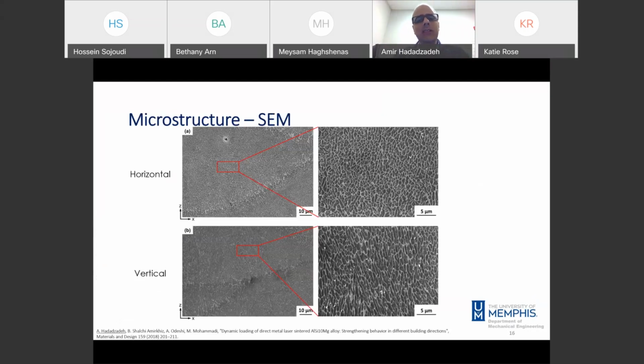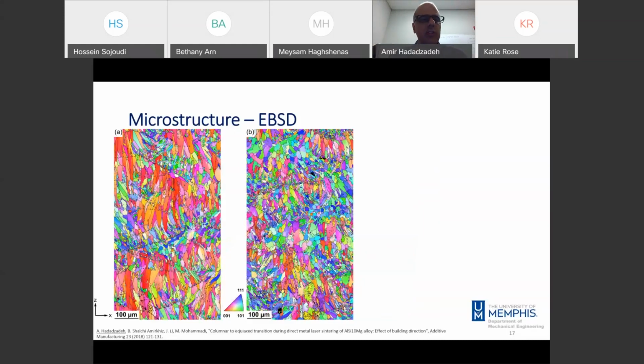we will have a different grain structure. So here, in the case of the horizontal sample, I didn't want to go through the details because it's a long and complex topic considering the solidification in the material. But generally, I observed that by changing the geometry from horizontal to vertical, there is a change in the morphology of the structure. Here, more or less, we see an equiaxed cell structure, while in the case of vertical, we see a bimodal structure dominated by columnar structure. And we see the same trend in the grain structure.